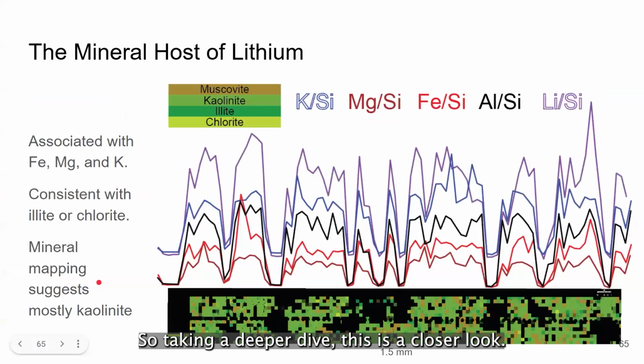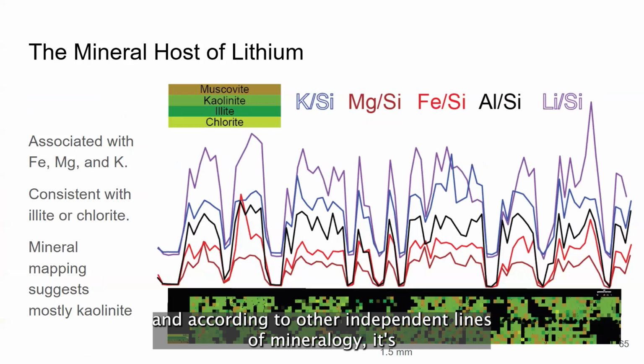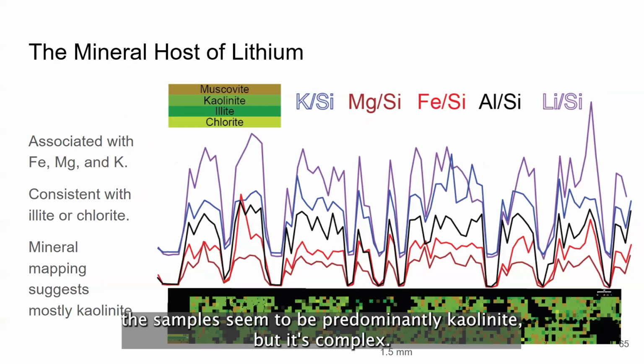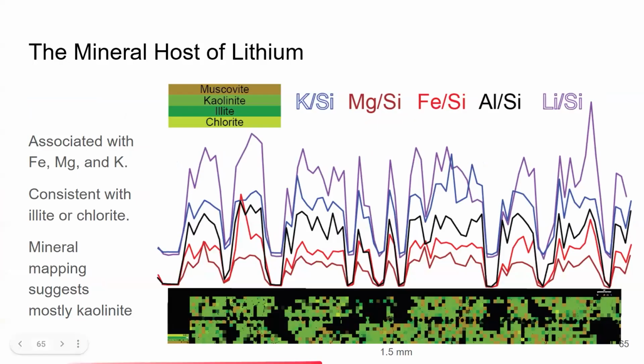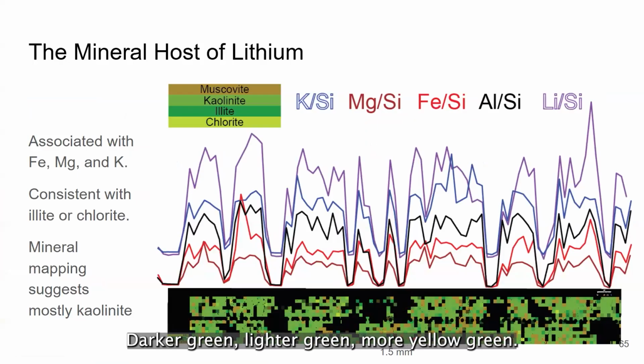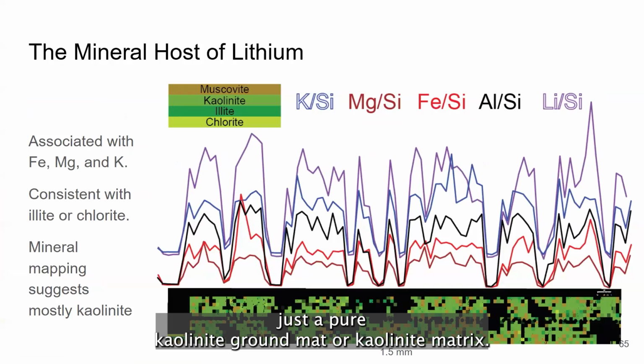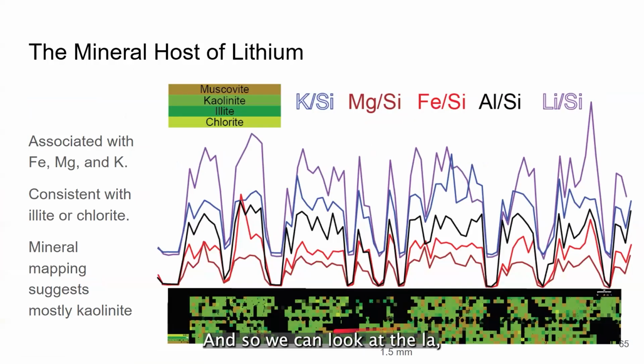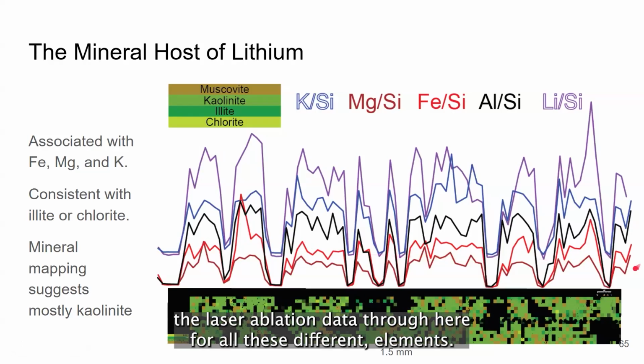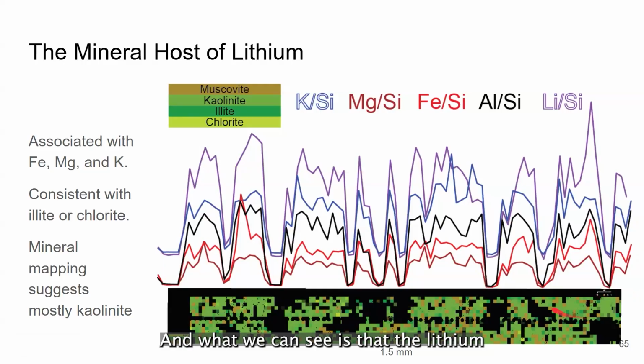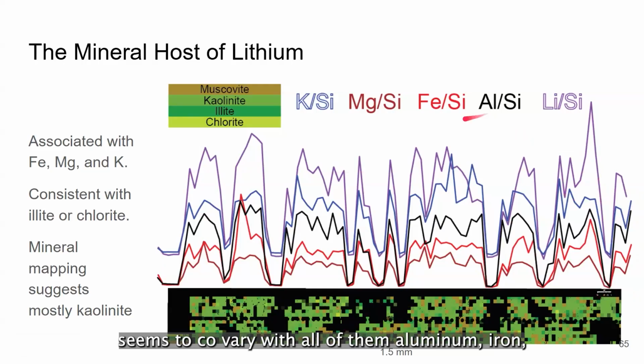So taking a deeper dive, this is a closer look. According to the mineral mapper and according to other independent lines of mineralogy, the samples seem to be predominantly kaolinite, but it's complex. There's little brown pixels in there, darker green, lighter green, more yellow green. So it doesn't seem to be just a pure kaolinite groundmass or kaolinite matrix. It seems complex. And so we can look at the laser ablation data through here for all these different elements. And what we can see is that the lithium seems to covary with all of them: aluminum, iron, magnesium, and most notably potassium.